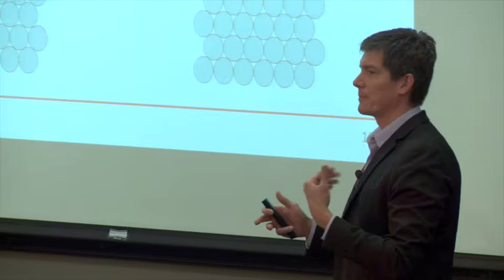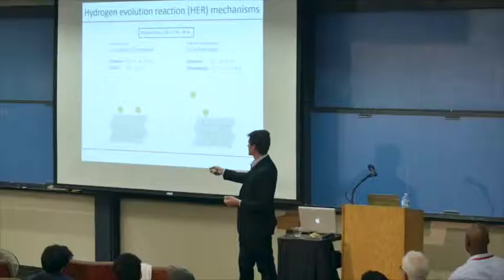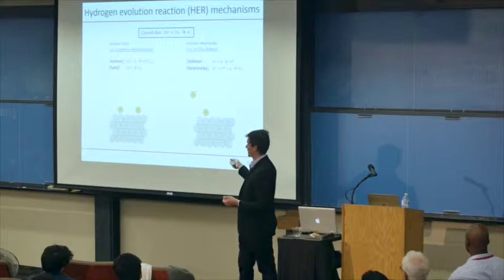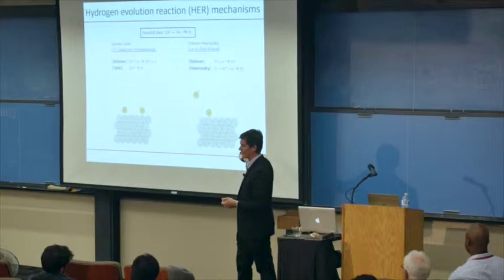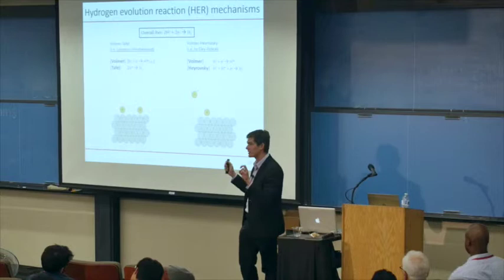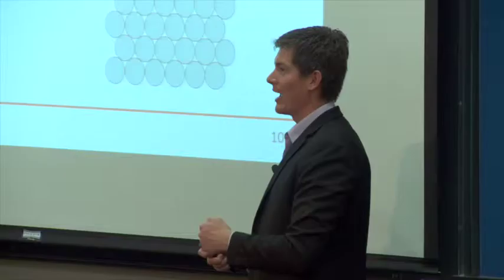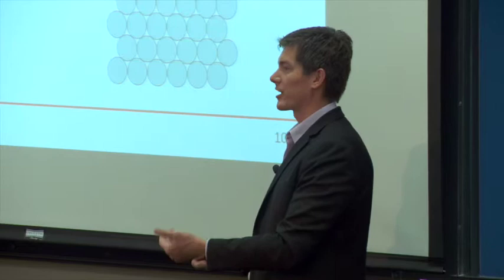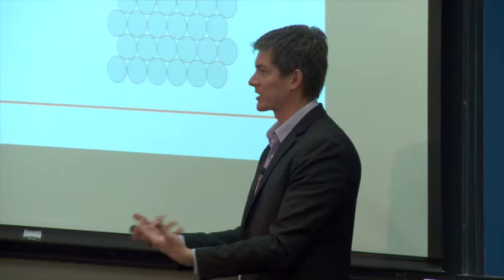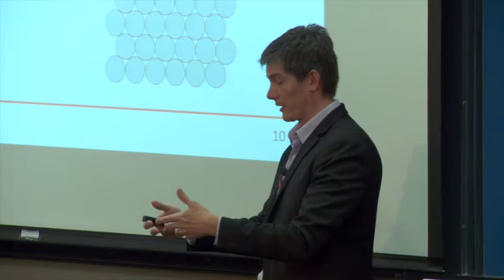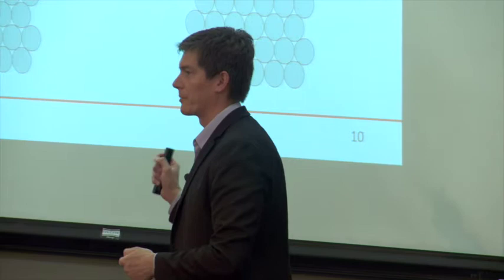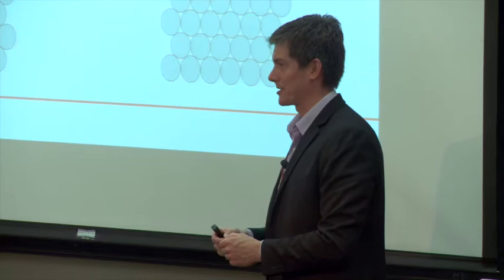One of the big challenges in our world, experimentally, is that this is a PowerPoint drawing of a surface. And it's a beautiful drawing of a surface, nice and flat and ordered. In real life, it's really hard to make electrodes that are so flat and so ordered, and even single crystals that you can buy or make yourself will have defects. And then those defects participate in the reaction as well. So what you're really looking at is a superposition of sites that are all behaving a little bit differently. And that's why real materials that you make don't follow the rate laws that one draws up using paper and pencil theory. And that's part of what makes it so challenging. That's an excellent, deep and fundamental question. All right, so with that, thank you all very much for your time and great to be here, thank you.